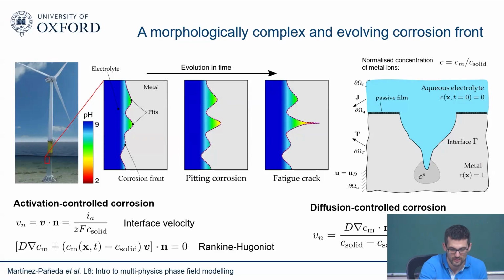Yeah, that's no problem. Similarly, this model will work only if we have pitting initiation happening in the chloride environment. You're wondering whether you can nucleate a pit with the model as well? Most of the materials we are using are basically aluminium based, either for aerospace or so, and they have a tendency to have a very thick passive layer of alumina. So again, these models won't work in that case if passive film formation is taking place, because the model is not taking the passive layer into account. It will come. Because this is an important coupling with mechanics, right? So what do we do when we have corrosion problems? We use corrosion-resistant materials that develop a passivation layer that will prevent corrosion from happening. Then the way mechanics interplays with corrosion is that it ruptures that passivation layer, and then the passivation layer forms again. So there's an interplay between mechanics and corrosion. That will come later as well.